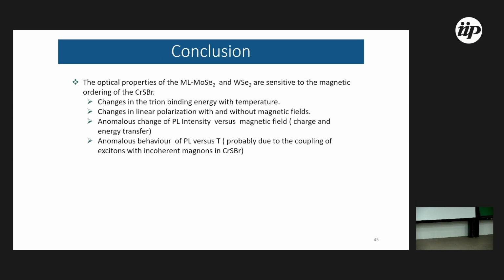So to finish, I have shown that you can have surprises when you use these materials. There was one question that people could ask, and I asked myself, why do you have this proximity effect if the magnetization is in the plane? You should not observe it, but we have observed splitting. I didn't show you splitting at zero field, depending on the position that is more coupled, we have a splitting at zero field. The main reason is that when you have the MoSe2 that has quantization perpendicular and the magnetization in the plane, by this interaction, you can tilt the magnetization of CrSBr, and so you can observe this. This was shown theoretically and experimentally in another work that I participated in with the people from Regensburg, but I don't have time to show everything.